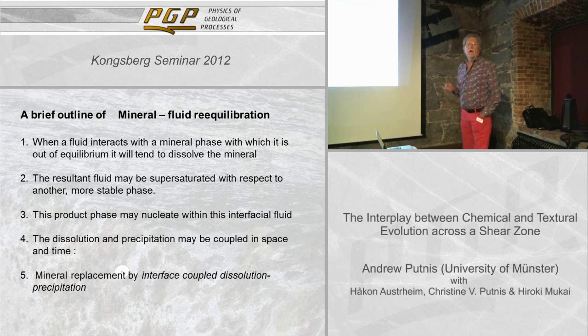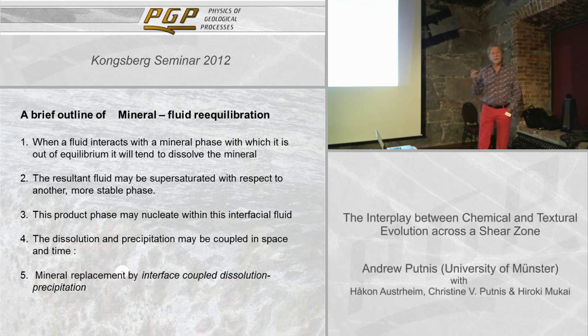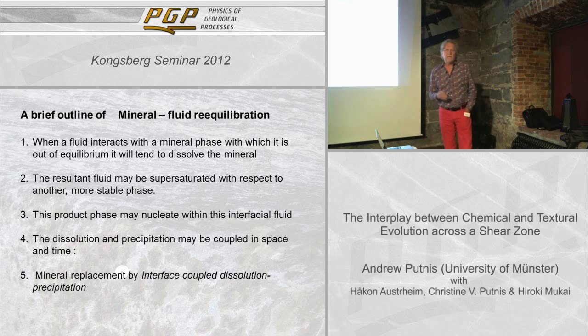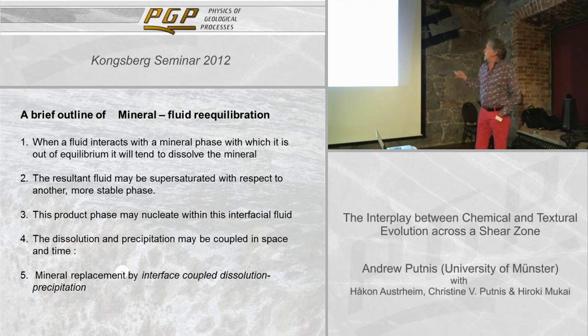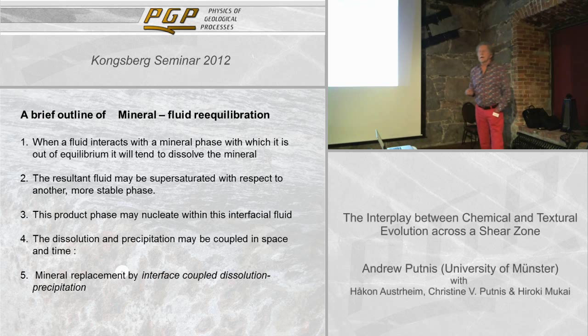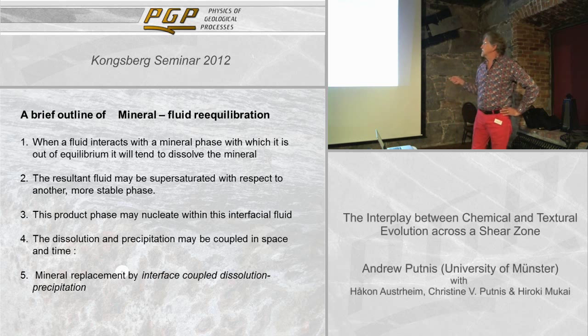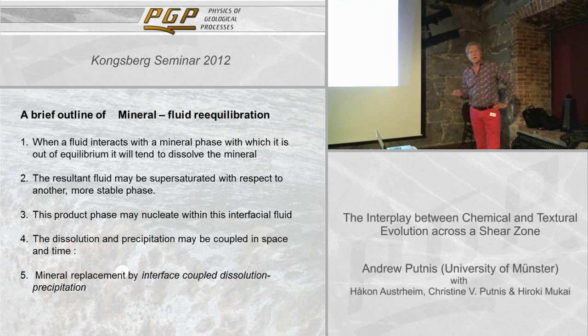Because as soon as you dissolve a small amount of solid, if that interfacial fluid is supersaturated, you have the possibility that it will nucleate — and it will nucleate, perhaps, on the very surface that's dissolving. And you will set up an autocatalytic feedback, such that the rate of dissolution will be faster because you have a solid nucleated on the surface. There's a lot we could say about what controls nucleation kinetics, but I won't say much about that, except a couple of things a few slides on.